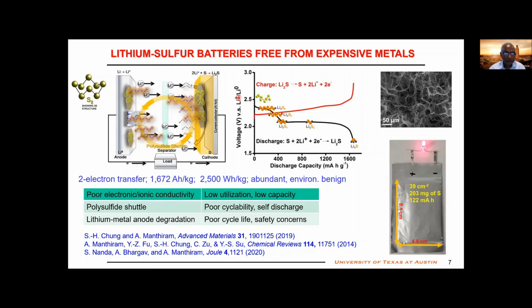Also during operation, these rings break, you form chains like this, and these migrate from the sulfur electrode through the separator, liquid electrolyte, into the lithium metal anode, and that causes a lot of headache. Because sulfur does not contain any lithium, you also have lithium metal here that has its own safety problem as well as reversible deposition problem. They form dendrite or massive structure, a lot of issues.